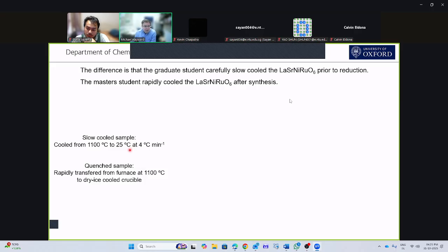So what we're going to do is take a sample of LaSr-NiRuO6, heat it up to 1100 degrees C. And then half of the sample we're going to cool down slowly at 4 degrees a minute down to room temperature. And the second sample, we're going to take it out of the furnace and drop it into a crucible cooled by dry ice. So we're going to cool it as quickly as we possibly can. And then to these two separate samples, we're going to add calcium hydride, seal them in a glass tube, and heat them for 4 periods of 48 hours at 360 degrees C.